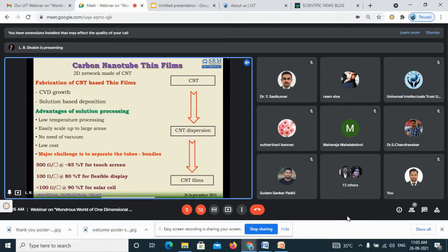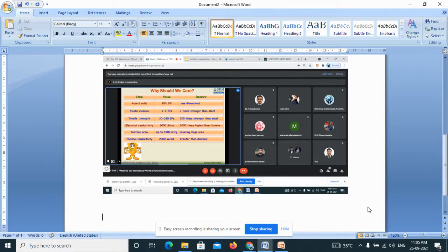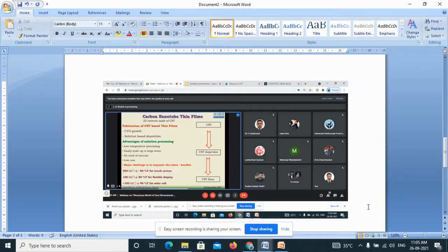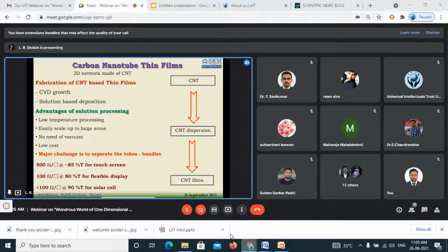So still I'm looking at the solution-based process because it has an advantage. You can use it at low temperature, and compared to CVD growth, this solution processing will have a very low cost. The cost for this method is very low compared to the CVD process, and you don't need a vacuum. You don't need to work with a vacuum system in order to produce a transparent film using the solution process. So as I already mentioned in the previous slide, depending upon your sheet resistance as well as transparency, you will find potential applications.